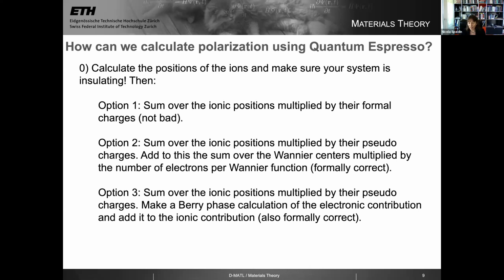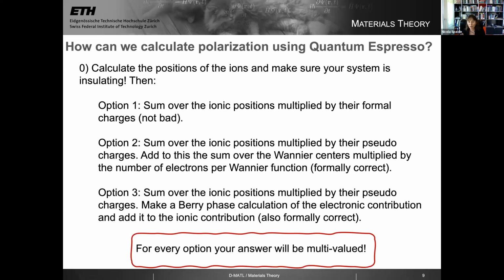So you can take any of these methods, but what you have to realize is whatever option you take, your answer will be multi-valued. You will never get just one answer. You'll always get the answer plus n times this polarization quantum. And that you can't get around. It's not wrong. That's really the way bulk polarization in a periodic solid exists.